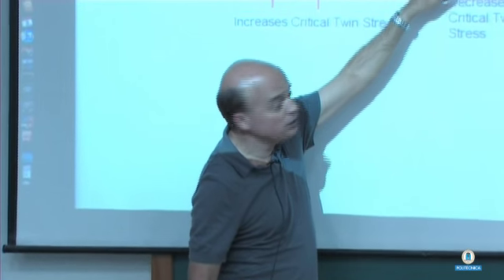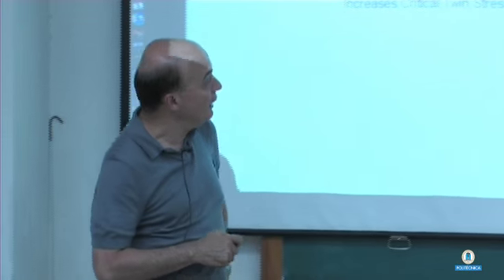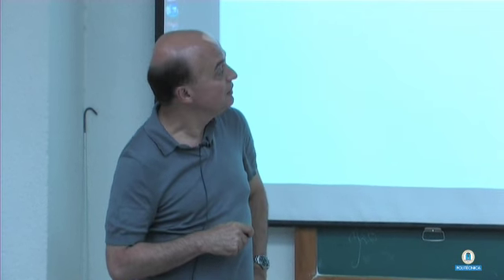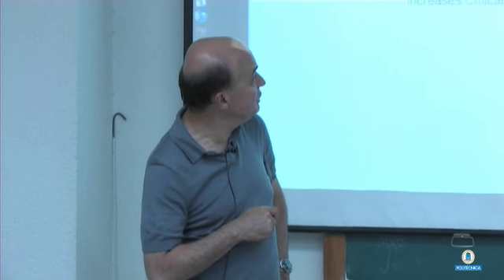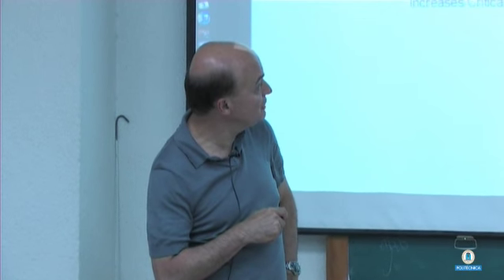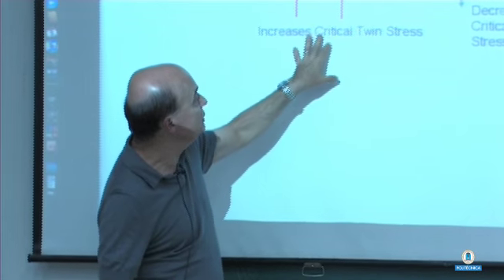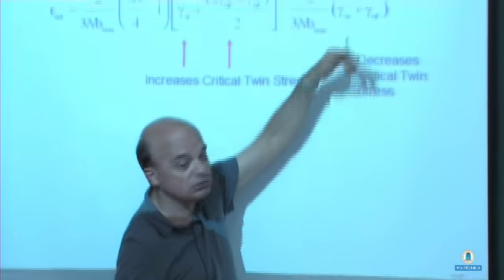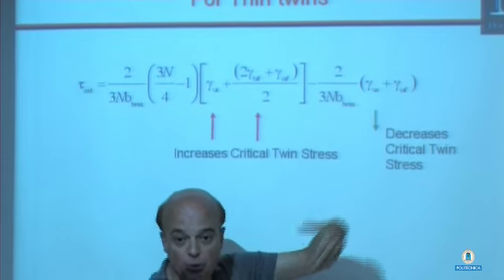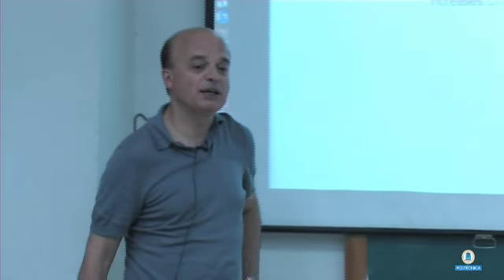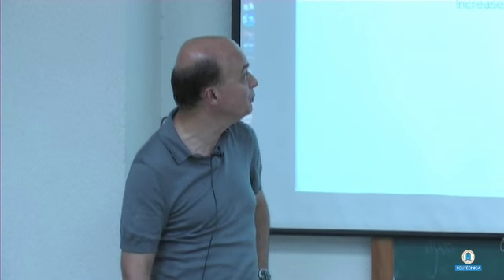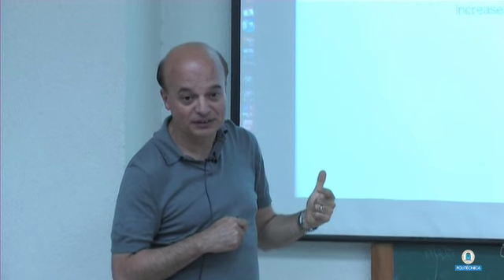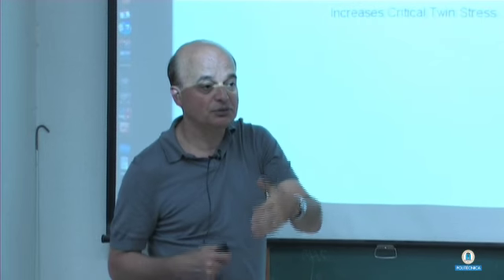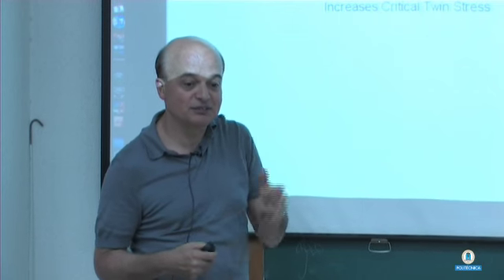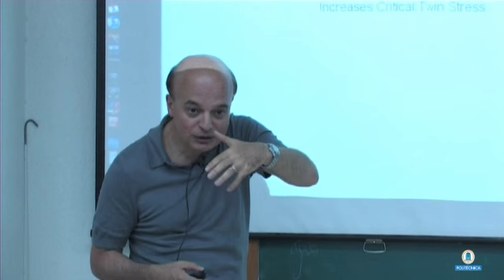And the interesting thing is gamma US is also playing a role, and an increase in gamma US will decrease the critical twinning stress. So an increase in ISF or 2TSF, these two terms are almost equal, will increase the critical twinning stress. The increase in gamma US will decrease the critical twinning stress. This opposes it. This is like a competition between slip and twin. So this is the critical stress for twinning. Of course, if this value is very large, because of these numbers being very large, you'll likely get slip deformation. But if this number is small, you'll get twinning deformation.